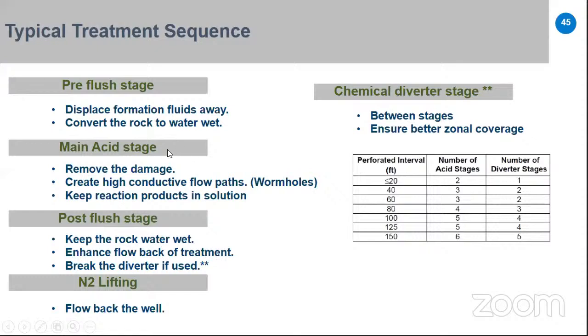Then we have the main acid stage, and the main factors in selecting the acid are the depth of the damage and the temperature of the reservoir. The main function of the main acid stage is to remove the damage and to create highly conductive flow paths, usually called wormholes. The third function is to keep the reaction products in solution. Then we have the post-flush stage. In this stage, we should also keep the rock water wet to make the flow back easy. In the post-flush stage, we can also use some additive that breaks the diverter if we used it between the stages. Then we usually lift the well with nitrogen and flow back the well.